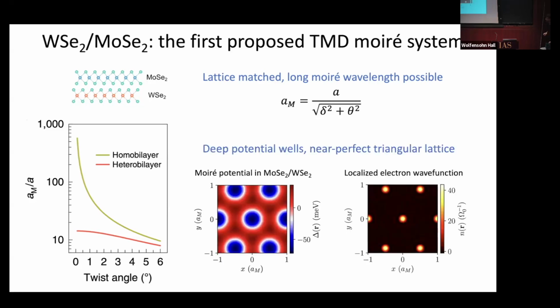wavelengths in the system. And the second unique property of this heterobilayer is that actually the Moiré potential is both very, very strong, of order 100 millivolts or so. That is, the potential wells themselves are quite deep. And also, it's almost perfectly triangular. So you can see that as you add charges one by one, they like to form very localized electronic wave functions at the preferred stacking real space stacking sites. And in fact, as you add more and more carriers per Moiré unit cell, actually multiple carriers like to sit in the same place because the Moiré potential is so deep.